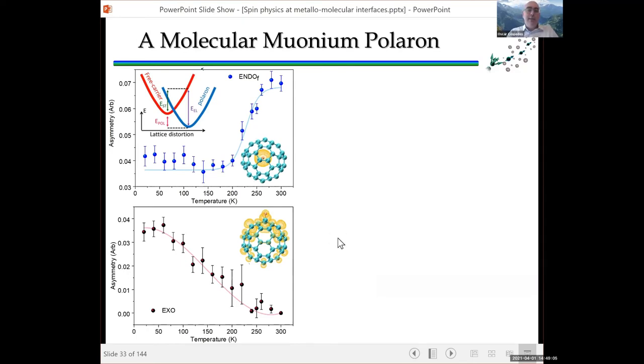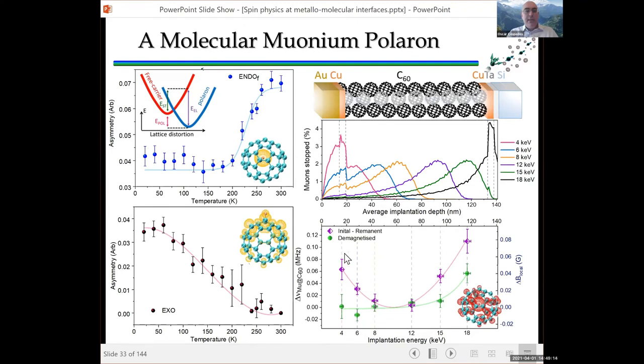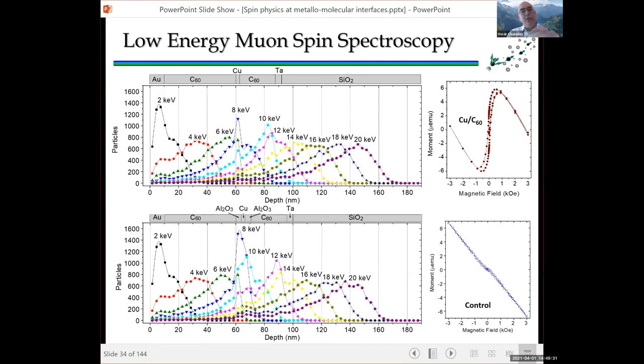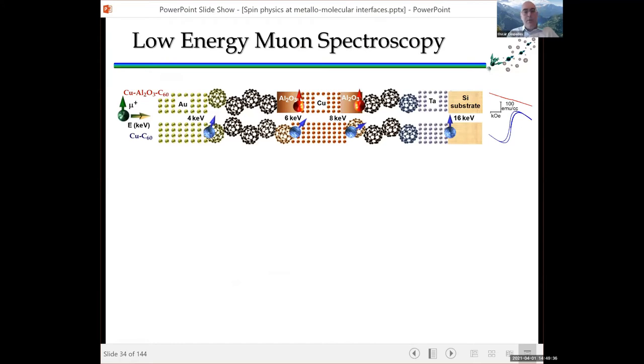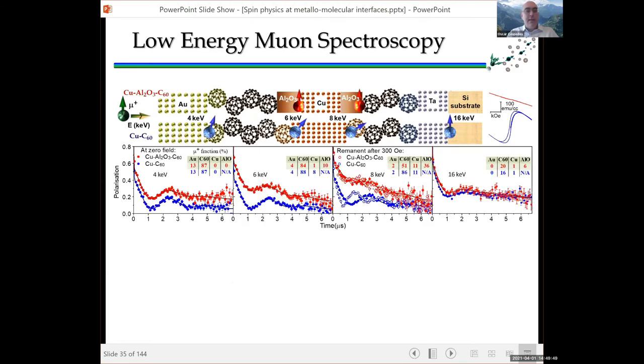And this muonium polaron has the peculiarity that it is very highly sensitive to the magnetic and electronic structure of your sample. So any changes in the local magnetization or the local charge density is going to change the frequency of oscillation of your muonium. So we can use this to detect very small magnetic fields, which we did in the copper C60 samples. So here we have two samples, one with the copper C60 interface, one without, and then we do our muonium spectroscopy measurements. And then you can see that comparing the muonium effects in samples that have this copper C60 interface, and samples that do not have it, we have different precessions that indicate different local magnetic fields due to this emergent magnetization of the copper C60 interface. So you have an increased oscillating frequency in the copper C60 interface due to the emergent magnetization.